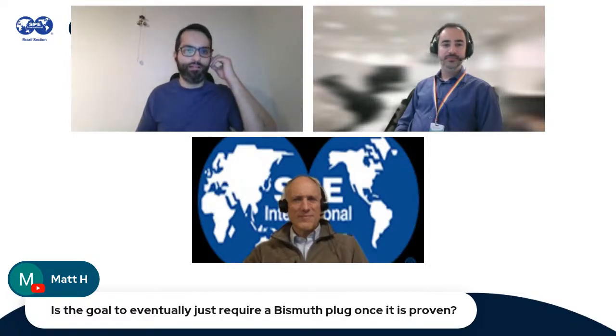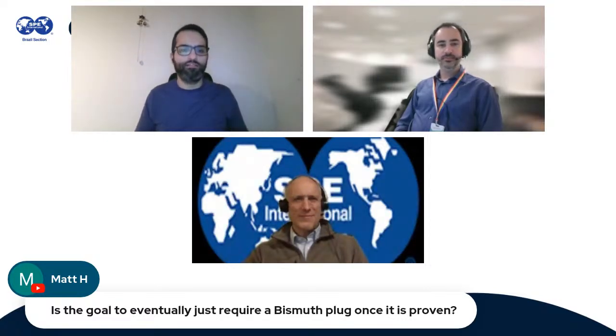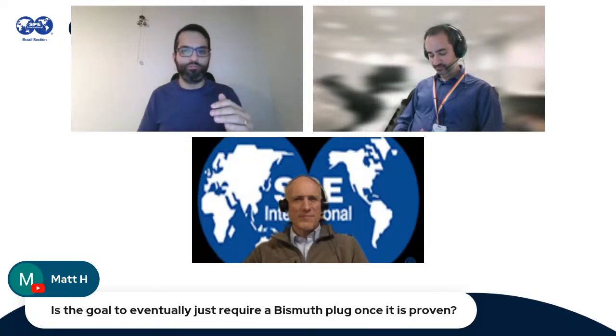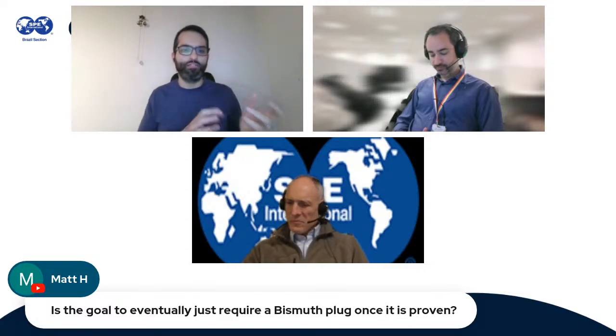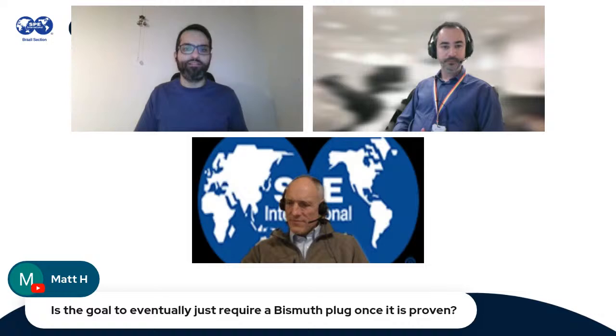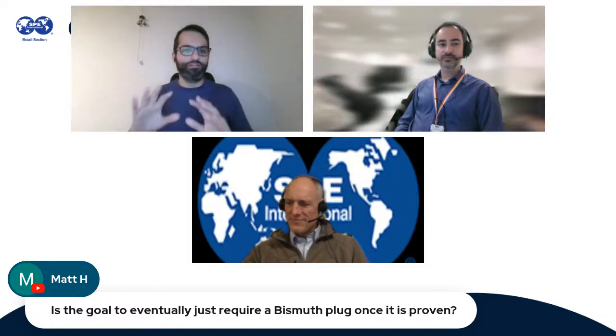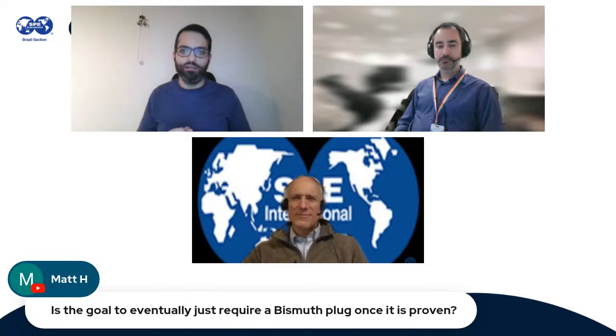So at least from the Aker BP field test that they did, they still had the cement plugs in place, and then they added the bismuth plugs on top, and then they could monitor what was happening along the bismuth plug itself. So they could see if a leakage was happening only on the bismuth plug. That was their way of testing this on the field, but at the same time still complying with the standard way of doing the P&A.